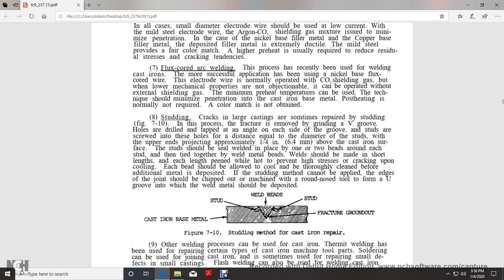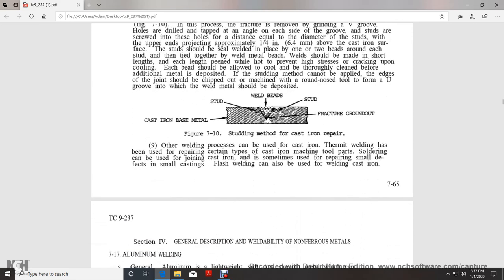The flux cored arc welding process has been used successfully for welding cast iron. The application used a nickel-based flux cored electrode wire, normally operated with CO2 shielding gas, but where lower mechanical properties are not objectionable, it can be operated without external shielding gas. The minimum preheat temperature can be used with this technique, and penetration into the cast iron base metal should be minimized. Post heating is normally not required, and a color match is not obtained.